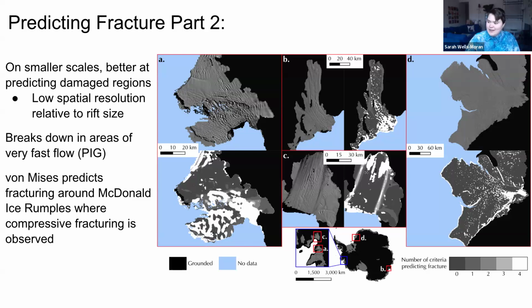Pine Island is a bit of a special case because all of the criteria think that this should just be incredibly fractured, and it's not really visibly fractured in 2014. So it kind of breaks down in areas of fast flow. And then what's also really interesting is von Mises is the only criteria that predicts fracturing in a compressive regime where there are fractures actually observed, which is right by the McDonald ice rumples on the Brunt ice shelf, which is outlined in yellow here. So quite interesting that von Mises is the only criterion that's able to pick up those compressive fractures.